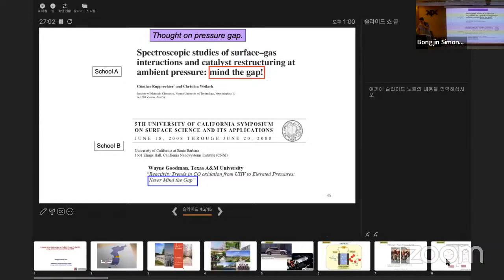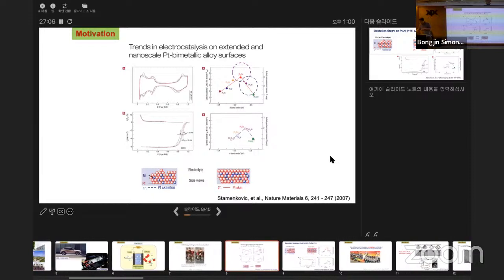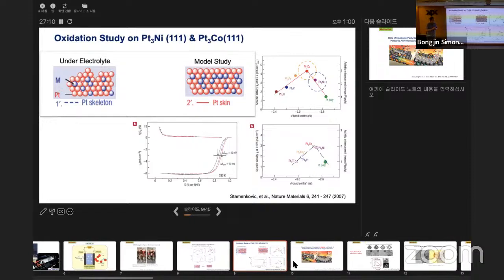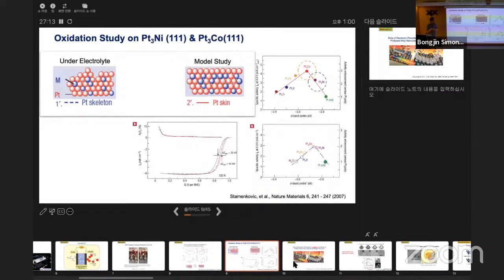Oh yeah, so the d-band center was suggested by the Danish group. In the DFT calculations, they looked at all the reaction trends, and previously people thought that the highest density at the Fermi level was probably the most reactive, because that is readily available for charge transfer. But it turns out the whole d-band, the weight of the center, is actually more relevant.